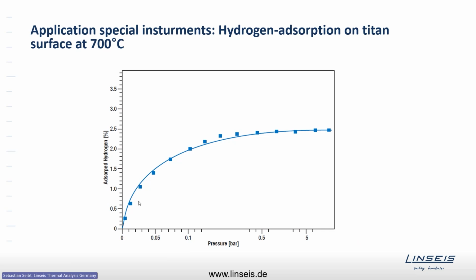The experiment was done again. It was repeated with ongoing pressure increase. And finally, the result shows you the absorption curve for hydrogen on this titanium surface at 700 centigrade. This curve shows you that from 0.5 bar onwards, the mass of hydrogen that can be sorbed by this surface was no longer increasing. That means the saturation level is roughly at 0.5 bar. And even if you go up to 5, 6, 7, 8, 10 bar, the saturation level is already reached.